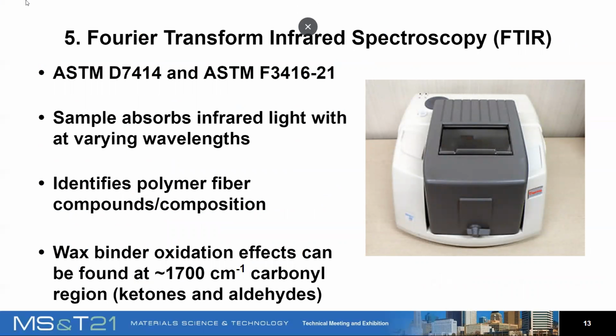Speaking of the FTIR, an FTIR can be used to determine the fiber content or multiple types of fibers present within the bulk of the track material. A sample is usually placed under a lens and it absorbs infrared light. The resulting curve from that absorption can then be used to determine the identity of the polymer. Oxidation can also be identified from this, and we'll see in the next slide where we can identify this. The carbonyl peak can also be plotted through a program.